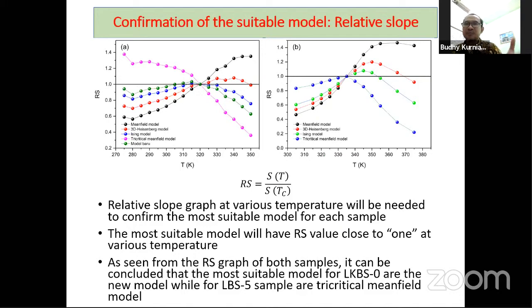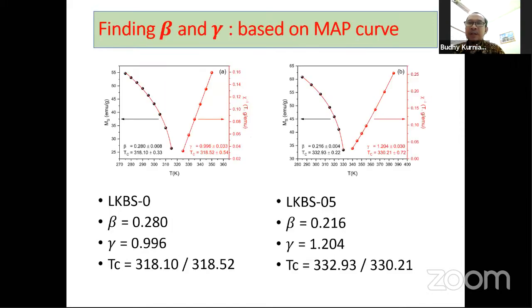We confirm the suitable model from the previous work by using the relative slope, and we confirm from this relative slope that the values of our gamma and beta are confirmed in this model. Also from here, we can find the value of beta and gamma for the LKBS 0 and LKBS 0.5.